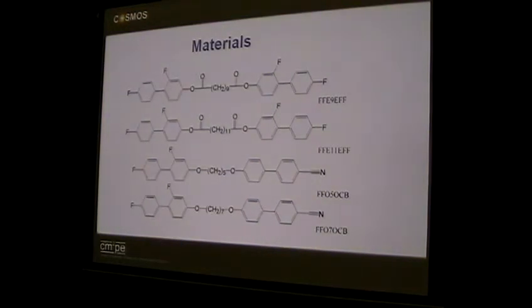And if you use the so-called high twisting power compounds that we talked about last week, you only need about 3%. You'll see when I come onto the blue phases after the break that in fact you get very high twists with 3.7, 2.4% additive. But you normally use highly chiral, highly twisted structure, as I think you even said last week, to imprint chirality into the system. And then you can tune it, which is the beauty. Are there more questions?